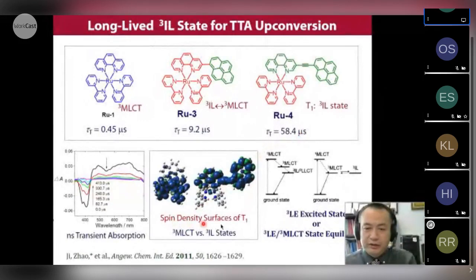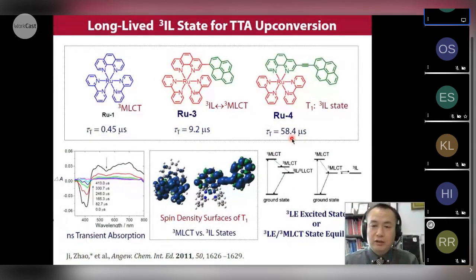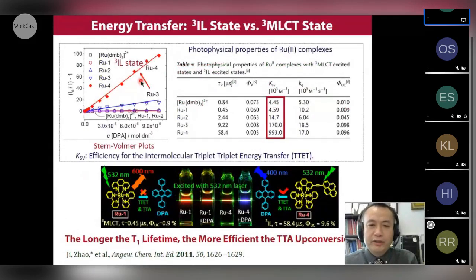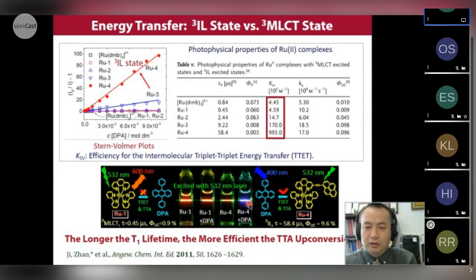From the spin density of the T1 state, we can see for the model complex, its MLCT state, the metal contributes a lot to the T1 state. But for the new one, the contribution from the metal is very small. That means we will have a weaker spin orbital coupling. Then we will get a much longer triplet lifetime. So with longer lifetime, we will have much more efficient triplet energy transfer in the TTA upconversion. That means we will have a much stronger upconversion intensity and efficiency.